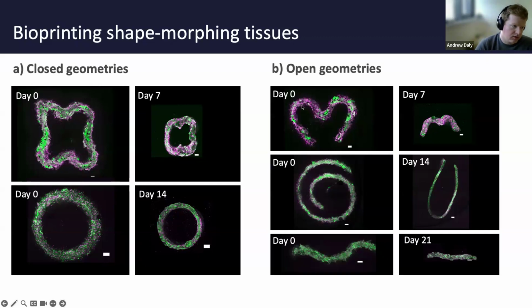So if we did these M-shaped structures or spirals, we found that due to the cell forces on the ECM and on the tissue, that created a stress that had to be dissipated. So the structure changed shape over time. It gradually opened, and you can see that here. So this was nice. We could print something and we could see it evolve over time within this support bath that I showed before.